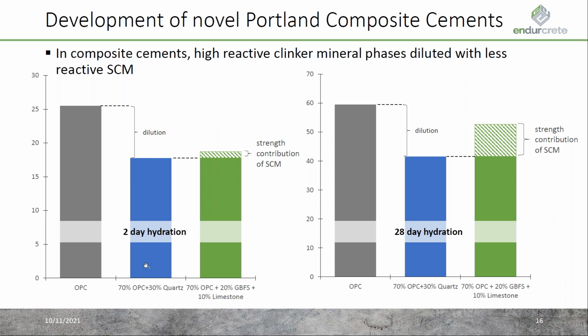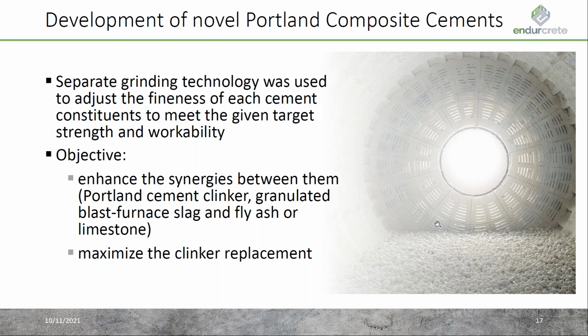If we take reactive materials, which are described in the cement standard, for example, granulated blast furnace slag in a mixture with 10% limestone, we have a very tiny effect on the early strength development by these constituents. But on the right side, you see the graph for the 28 days. And after 28 days, we have a significant improvement in strength because of the reactivity of the slag in combination with the clinker and the limestone. But even there is a gap which we have to close. And the way to close this gap, what we observed, is the technology of separate grinding of the materials. The last 100 years, most of the constituents in the cement were co-ground.